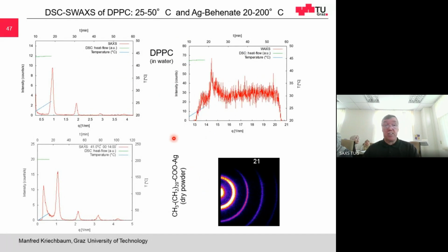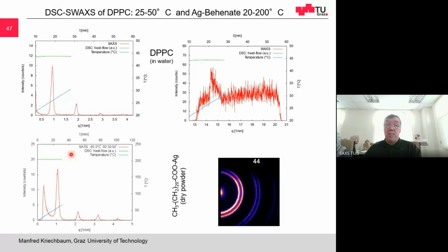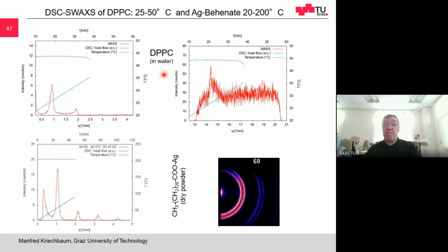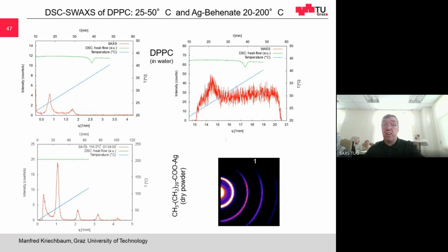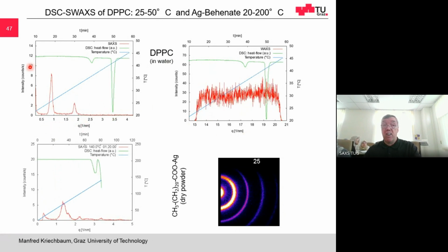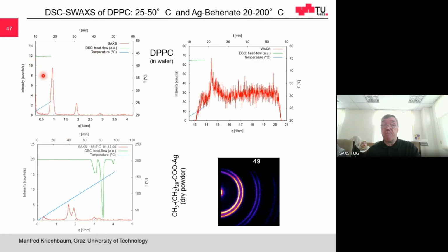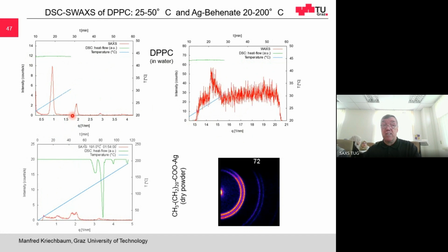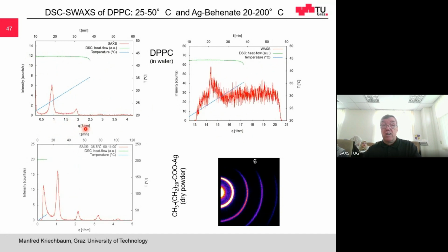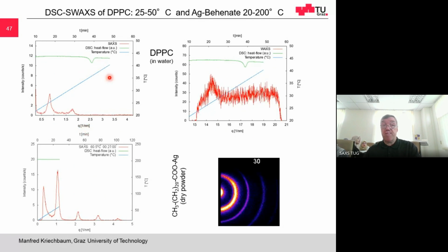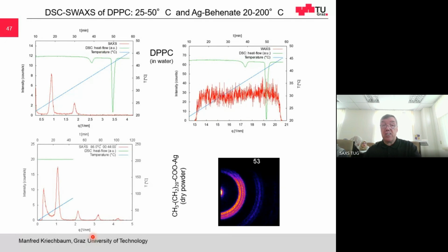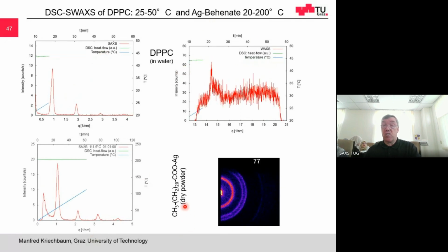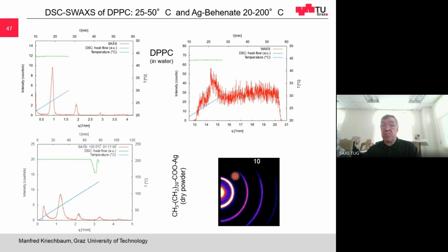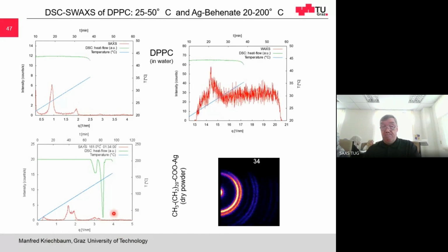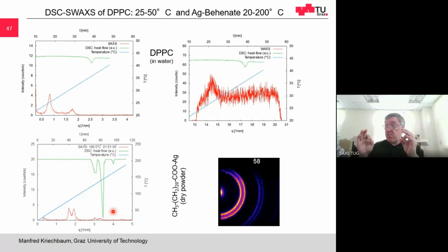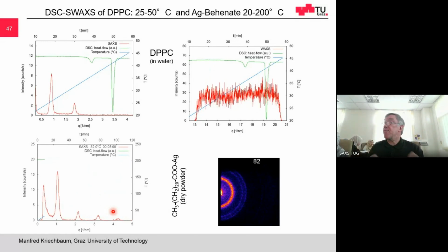Okay, here is again some animation. This is what I showed you before, DPPC. You see the change in the spectra. This is small angle, this is wide angle, and the green line is the thermal signal. See? The thermal signal is changing. Again, another transition. And here you have it for the silver behenate powder, for this compound. You can measure it also with a two-dimensional detector. So this is very important: thermal signal and nanostructure at the same time.